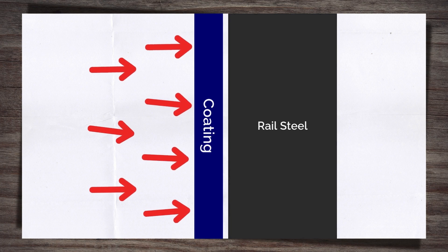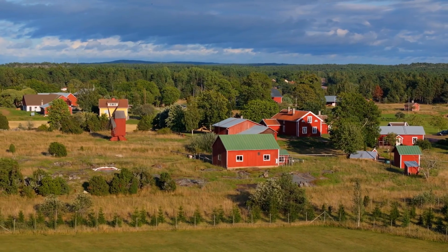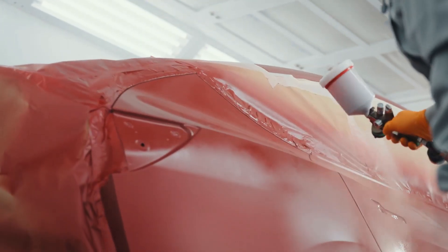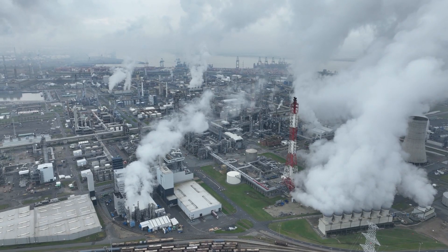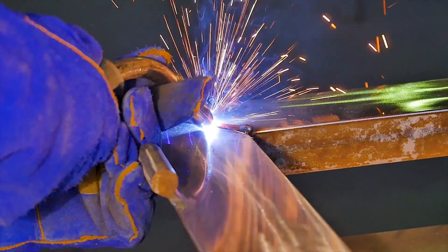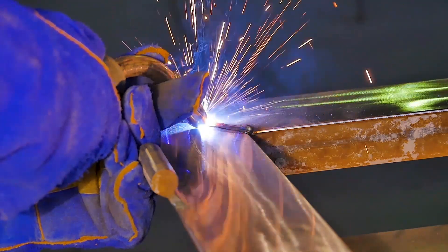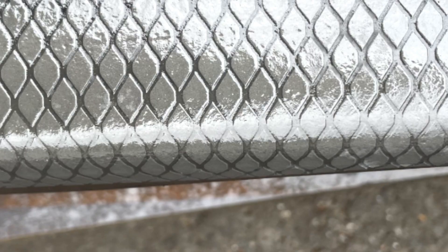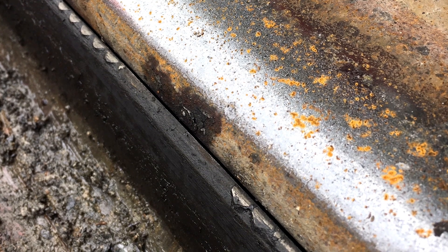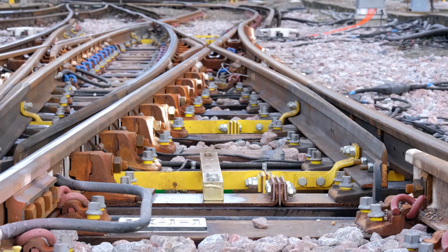Apart from changing the type of steel or giving it some heat treatment, how else can a rail be manufactured to protect it from life as part of the railway track? The answer is coatings. A coating provides a barrier between the steel of the rail and the environment it's placed in. Primarily used to prevent the corrosion of the rail, particularly the foot, coated rails are often installed within tunnels, level crossings, or other wet areas such as coastal routes. They may also be used in areas where other substances could damage the rails, such as yards handling chemicals. Coating of the rail does present one problem, and that is welding the rails together — often the coating has to be removed to allow welding to be undertaken, which then leaves an area of rail exposed without protection. As seen earlier, our sponsor Alphatech has introduced a coating that helps prevent wear on switches, opening up the application of coatings beyond their traditional use to prevent corrosion.